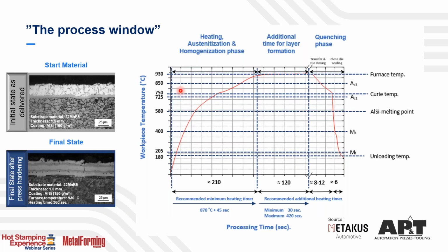And then the last slide I brought on the direct press hardening process is, I call it the process window. And I would be happy, this presentation will also be shared afterwards. This is how we set up our lines when delivering them out on the market. Basically, we have a time for the heating, and that is, as we heard before, depending on sheet thickness and surface composition. We heat up the blank to 870 degrees, and as soon as we reach 870 degrees, we add 45 seconds.